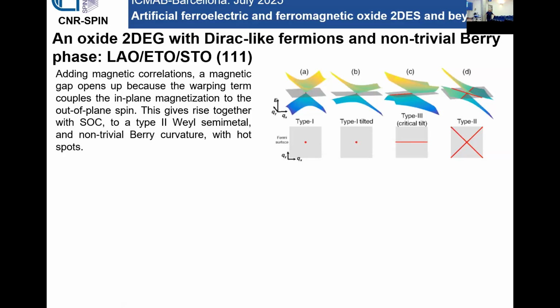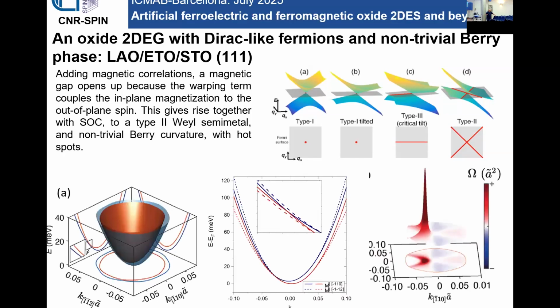But in our system, there is a time reversal symmetry breaking, because we added magnetism in the system. And when this happens, essentially in zero magnetic field, so without application of any magnetic field, we should have more or less the same physics that I described before in the 1,1,1 LAO-STO in presence of strong magnetic field. So essentially, we have a system which is like a type 2 Weyl semi-metal. And here, if you work out the calculation, which was actually performed also by Yuchen, who is a very good guy in doing these calculations, you have more or less the same physics, but at zero magnetic field. I mean, you have an intrinsic magnetization.